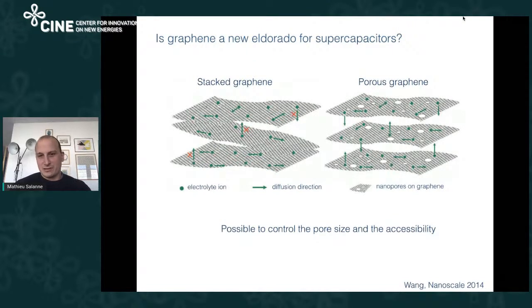Having porous graphene is not very easy because you have to make holes inside the structure, and so you can also lose a bit of the organization. For this reason, there is quite a large amount of discrepancy in the experimental results in the literature. The advantage of simulation is that we are not limited to a given type of structure, and so we can easily have perfect structures that we can control for sure.